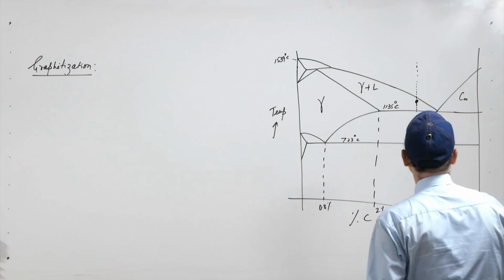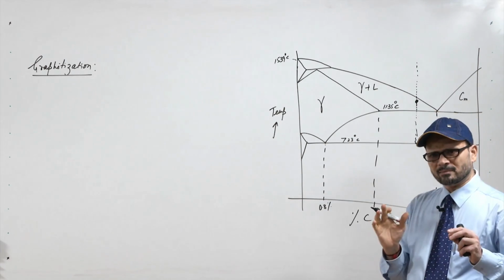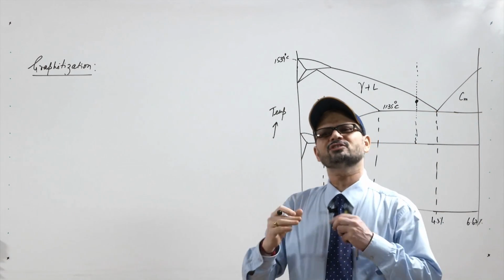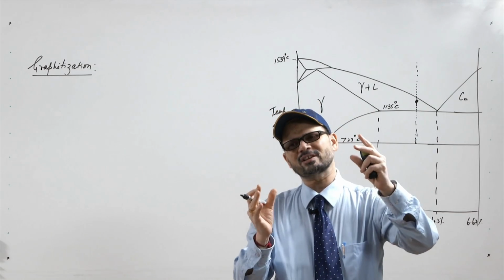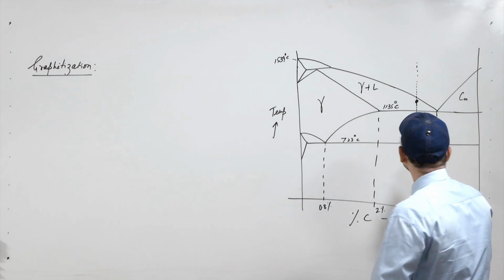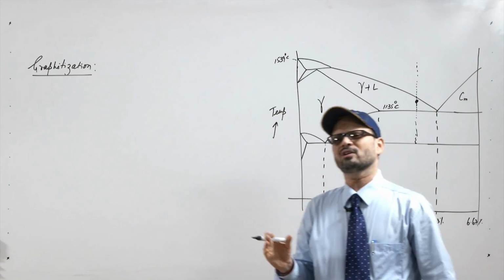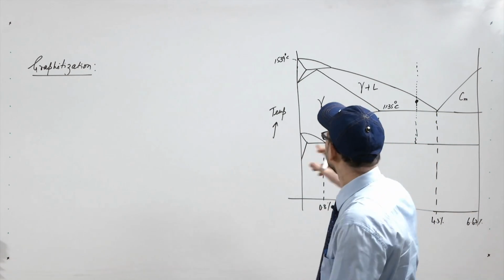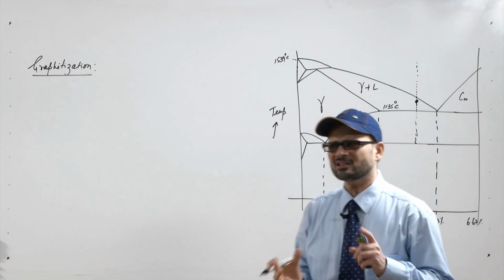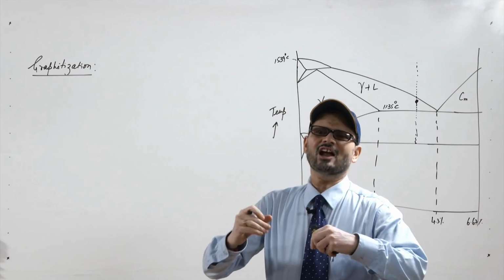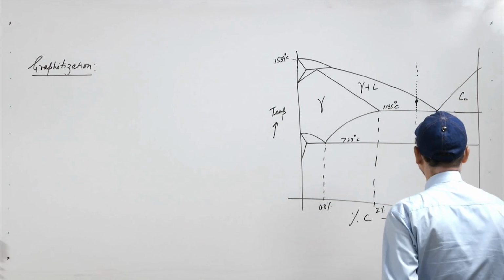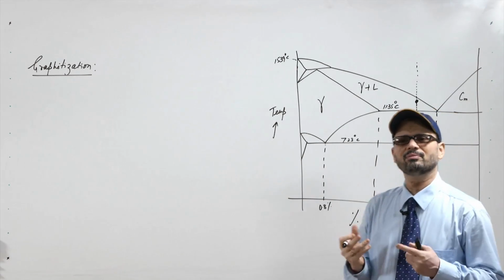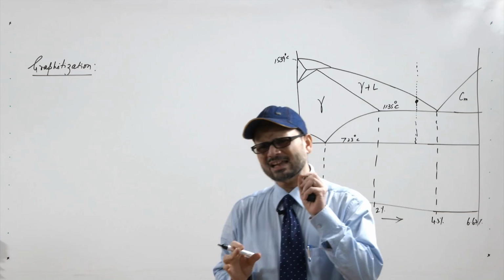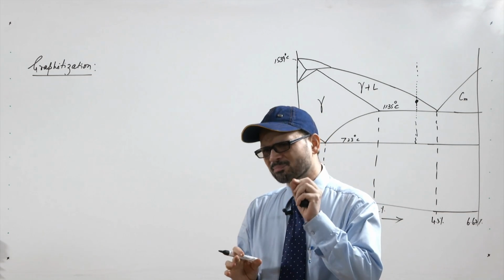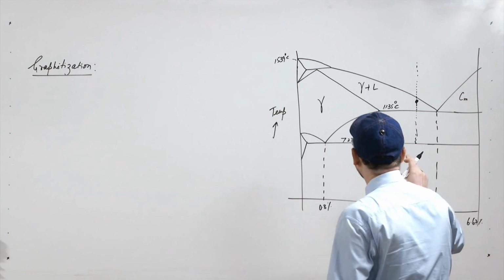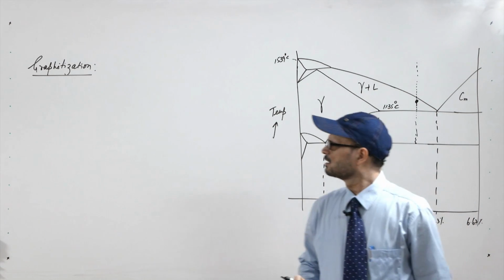So, when the graphitization is high, and the rate of graphitization is better, in that case you get a ferritic matrix. If the graphitization is not so high, maybe because of not an adequate amount of silicon present or maybe because of a slightly larger cooling rate, in that case you may get a pearlitic type of matrix. So, basically silicon is working as a principal alloying element which controls the microstructure of these cast iron components.